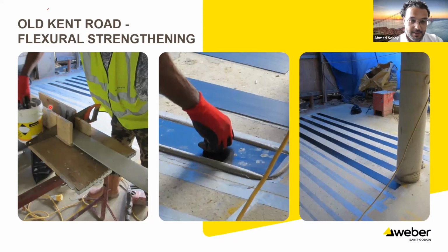It's a wooden box completely filled with structural adhesive, and they start with the plate from the top of the box, and as they pull it, they use this saw in here to control the thickness of the structural adhesive. As they pull the carbon fiber plate from the other side, you get a uniform layer of structural adhesive on top of the plate, which is obviously the objective. Another layer of the structural adhesive is laid on the floor, and you apply them wet on wet. You use a roller to pass over and press on the plate to release all the air entrapment and remove all the voids, and then all the excess material is removed, and this is what you end up with, a completely neat application of flexural strengthening.